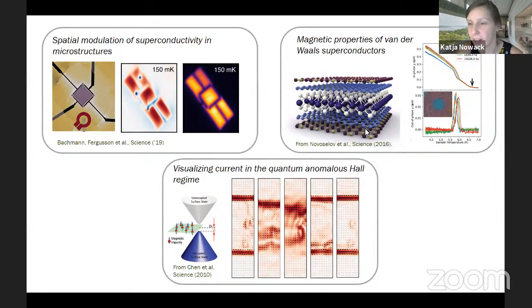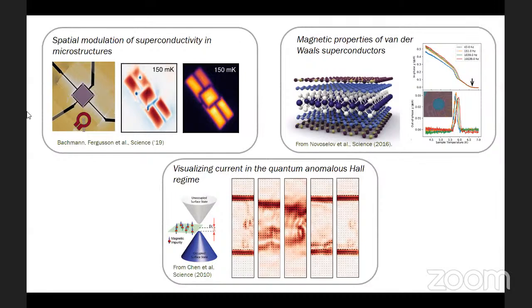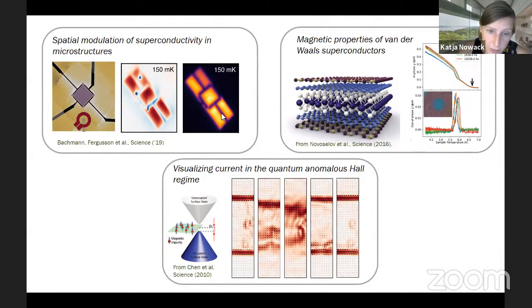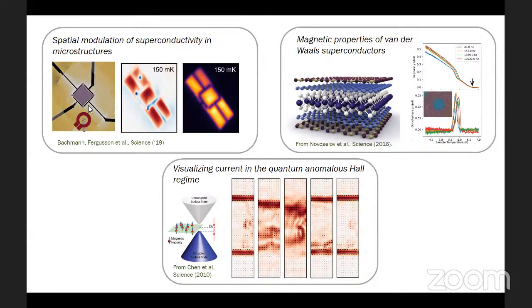It's complicated also because it's very hard to do the simulations. If you try to simulate how even a patterned sample responds to the measurements that we do, it's really non-trivial. So we can't answer the question easily even by simulations. We can look at line cuts through this kind of device, and you can see the trench in the device, but you can also see that it's not turning fully black. There's no superconductor right here in this trench, and yet the color is still some dark purple. So even in the middle of the trench, we get a mixture of signal from this side and this side of the device. And the trench, how wide is that? That's a good question. It's probably 5 microns in width or whatnot.